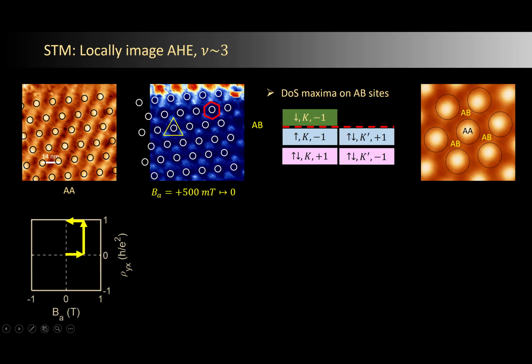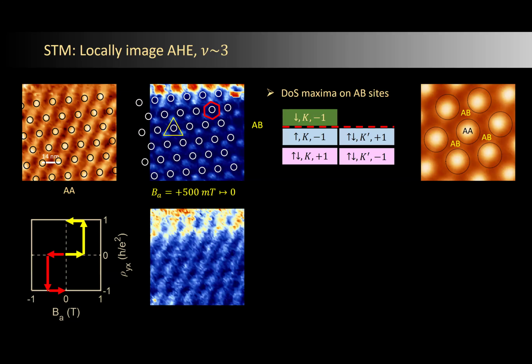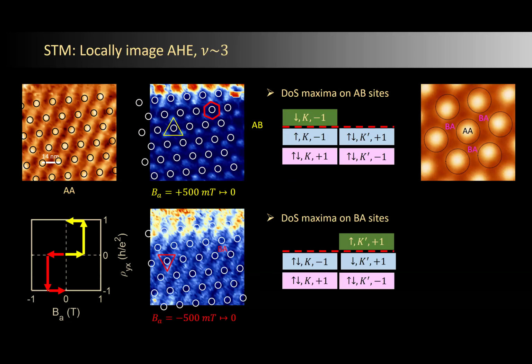If you shift, there's a correlation between the sublattices and the K valley. So it looks like we're sitting in one valley, and then we're going in the opposite direction of the field, half a Tesla, and then back to 0. The same excursion that the transport people did. And again, we put our AA points here. And now we see that the maxima have flipped. So there was a shift. And now it looks like they have shifted to the K prime valley. So it looks like what we have here is a finite Chern number. And it depends, just as in the transport measurement, on how you break that symmetry.